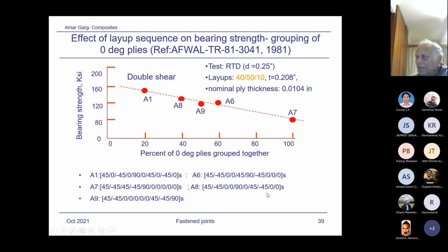The number of 45s is the same in every layup, and the number of 90s is the same in every layup. You will find 5 zeros here, 5 zeros here, 0, 0, 0, 0, 0. So that means 5, 5. Now you have the same number of zeros, same number of 45s, and same number of 90s in total. But in each layup, the bearing strength is different. The effect is due to bunching of the plies together. Now this is a phenomenon which, unless I could talk about the interlaminar stresses, is difficult to understand.